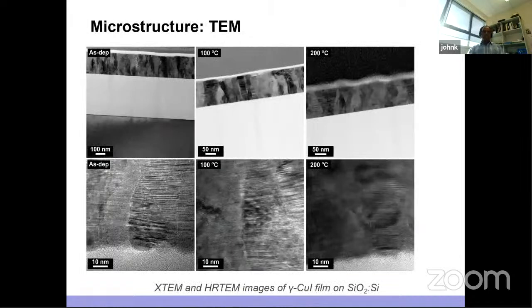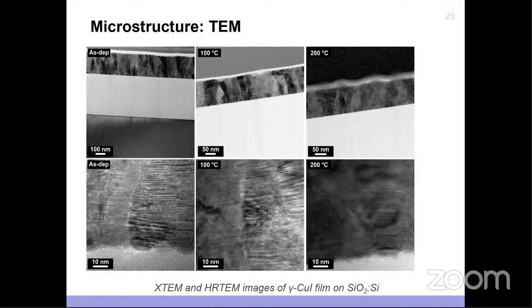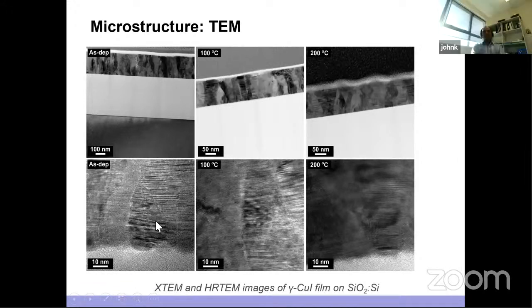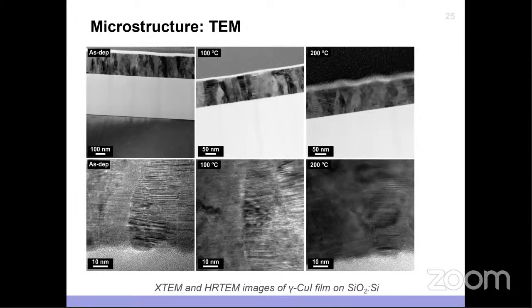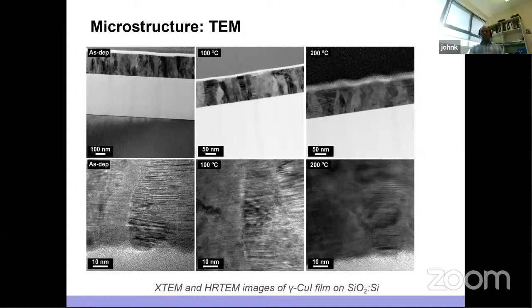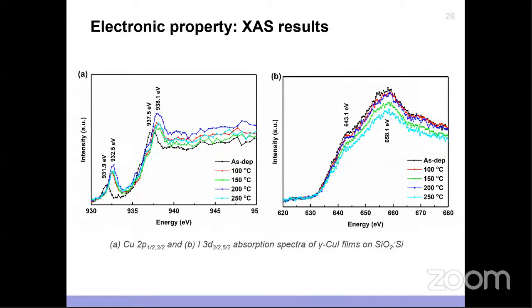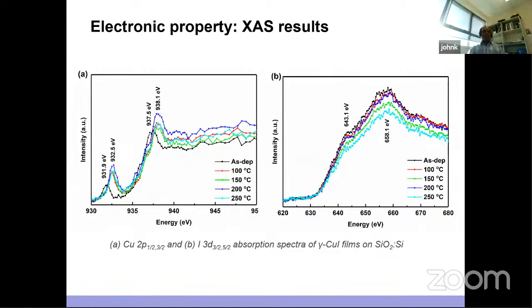What is more interesting is that if we look at the TEM image, we do see some nice metallic clusters. The tiny clusters are less than 10 nanometers. So that's interesting. These clusters can have an influence, but you can see the clusters are distributed uniformly after annealing. We've also done X-ray absorption spectroscopy to look at the band edge of these materials, and you can see that after annealing, the features become stronger, which indicates that copper zero-like defects increase due to greater migration from lattice sites. You see the pre-edge features on 3D-like copper vacancies, so you can easily see the change after annealing, which indicates that the defects are increased due to the migration from the lattice sites.